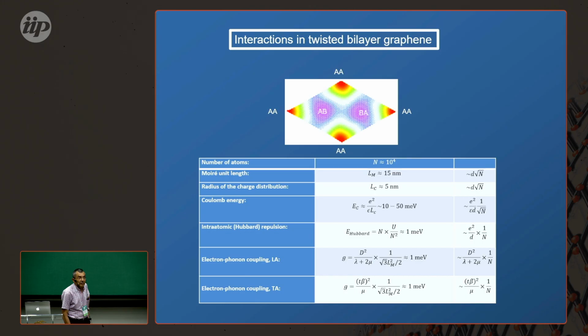So the density of relevant electrons, because the moire is so large, is very small, and because of that, most interactions, when projected onto the flat bands, are significantly reduced. For instance, if you have an intra-atomic Hubbard interaction, in order for it to play a role in the flat bands, you need 2 of these electrons in the flat bands to coincide on the same atomic orbital, and the probability of that happening is 1 over 10,000, 1 over the number of sites.